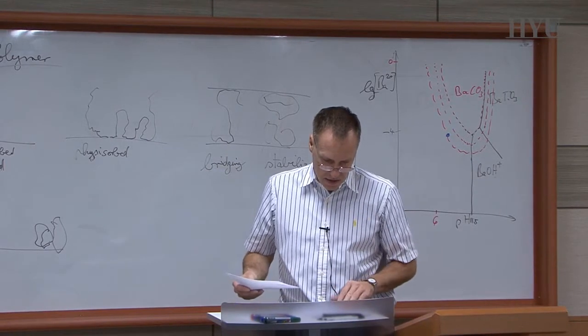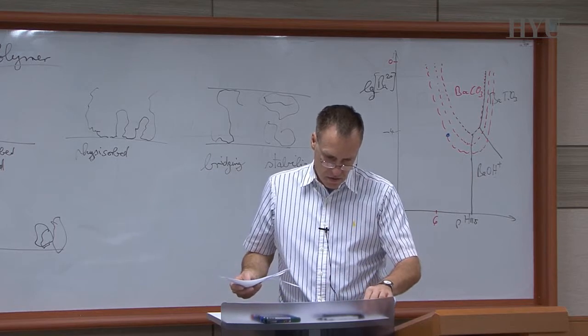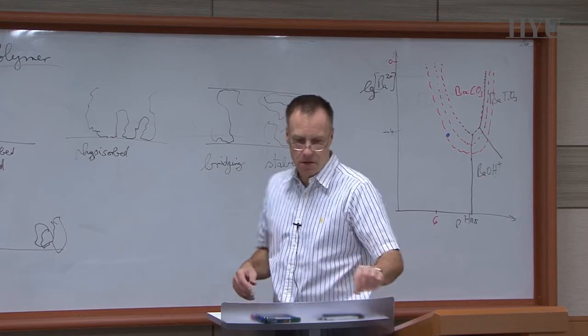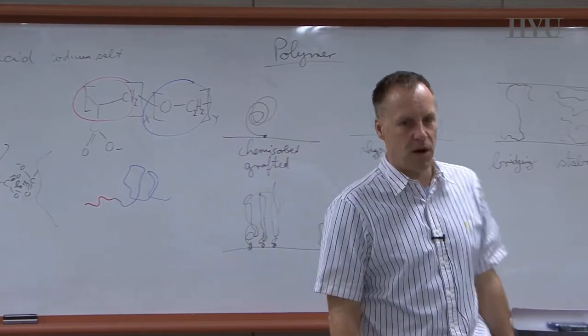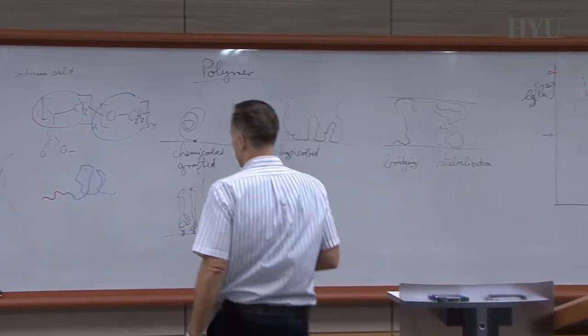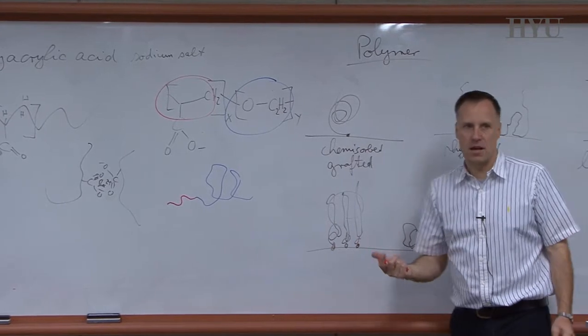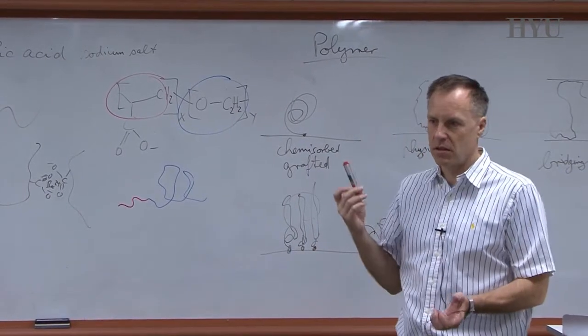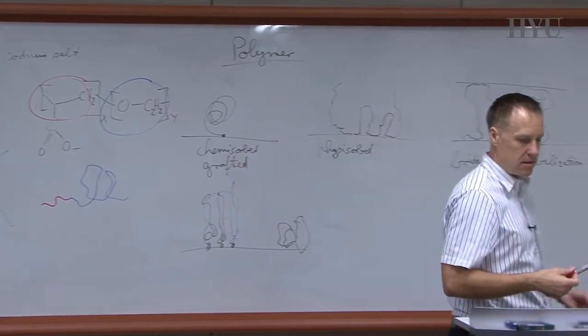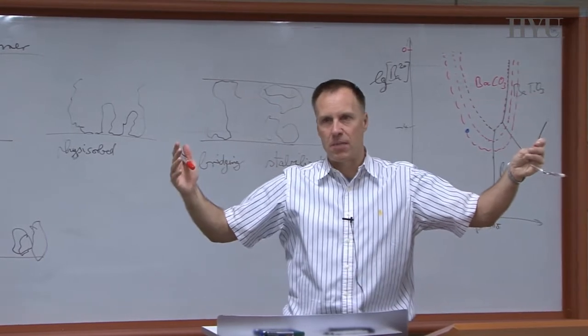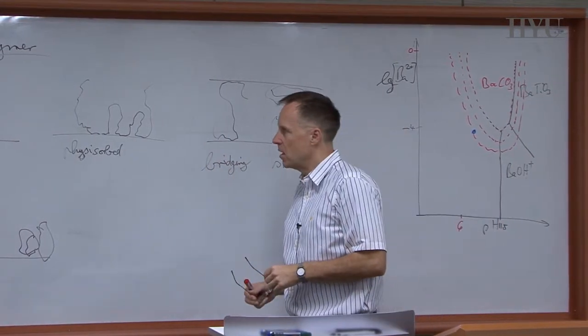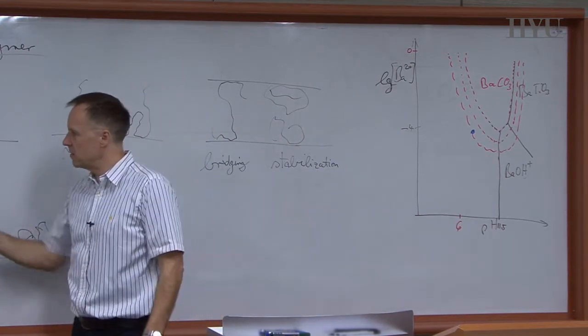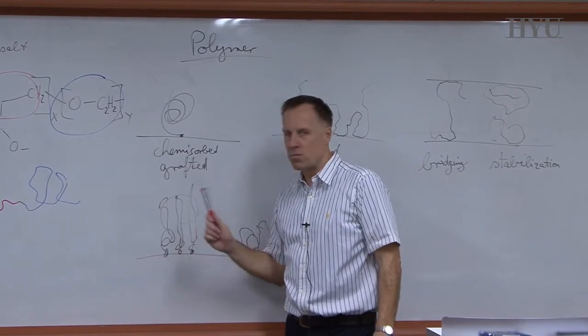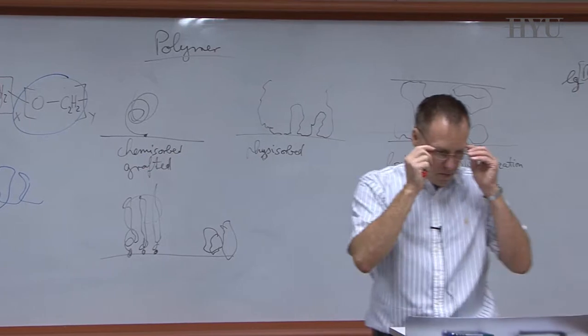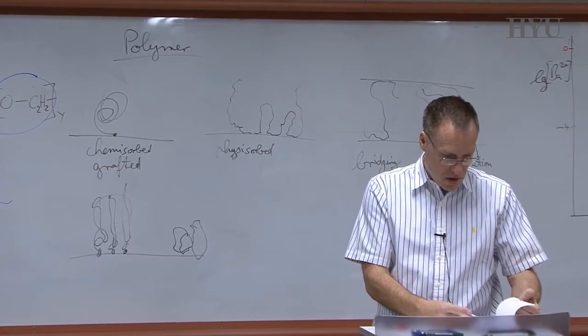And again, for these things, there are theories available. So you can do these things much more quantitatively nowadays. So you don't have to just experiment with different molecular weights. You can actually calculate what size of molecules you will need to bond. There are theories out there. There are typically three theories that are used. It's the Monte Carlo simulations, basically. There's then the mean field theory, where you average everything. It's a thermodynamic approach. And then there's another one called scaling theories. And for these compounds, typically the scaling theories work best, since you're talking about small molecules. And with this, you can approach the calculations in the best way. Okay.